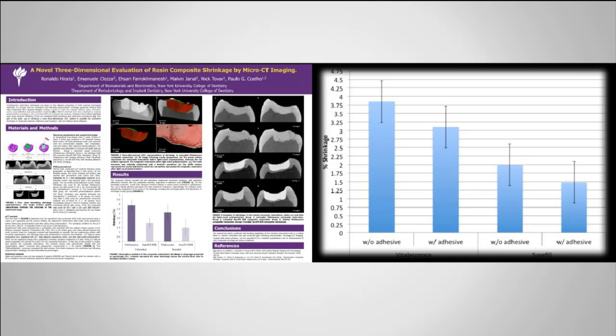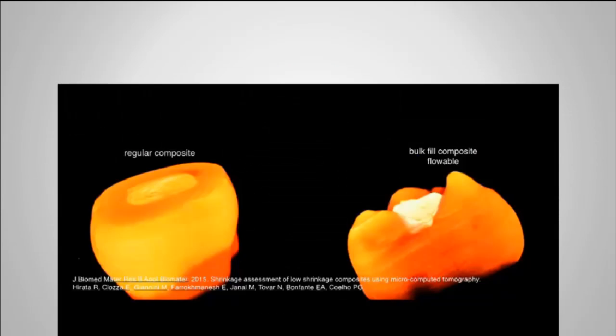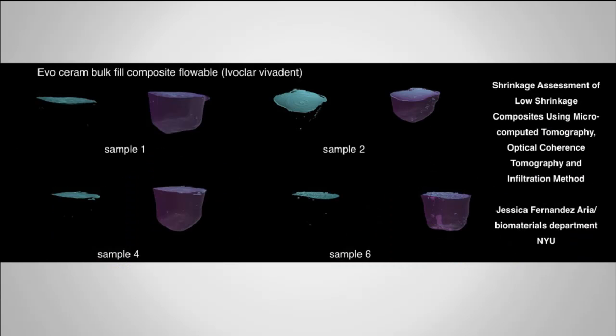In this technique of bulk fill composite, and we did some research on these bulk fill materials, you have less shrinkage and less shrinkage stress, and what you see in the interface is something interesting in the research. If you see these images of the bulk fill flowable composite from Ivoclar, these are 3D images of restorations. And in the green, the green shows us the shrinkage. So if you see these cavities filled with bulk fill flowable composite from Ivoclar, Evo Ceram, you can see that you have a small shrinkage only on the occlusal surface, but all the interface is sealed.